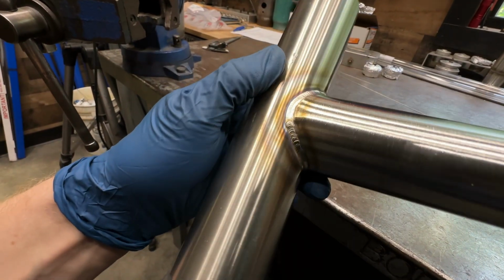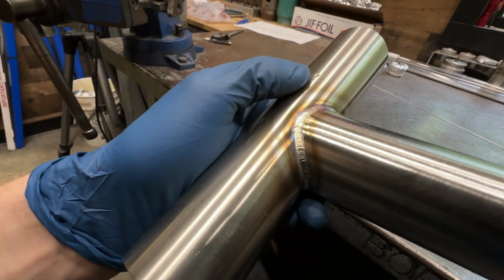You can see the weld is a little bit wider, the ripple is a little bit more pronounced through it, which is to be expected. Since you're using a larger filler rod, you have to apply more heat to melt the rod, which then will therefore apply more filler, and that's how you end up with the broader weld with a more defined ripple pattern.